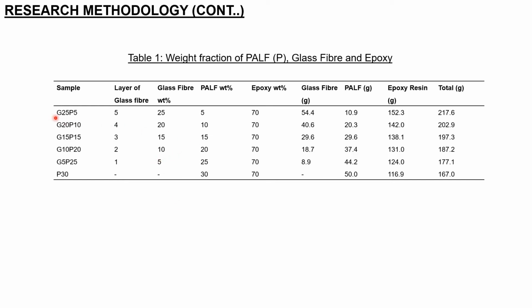Here is the table for the weight fraction of composition. The acronym G here is for glass fiber, 25 means 25% of glass fiber, P means pineapple leaf fiber, and 5 means 5% of PALF. The total percentage of glass fiber and PALF is 30, and the balance 70 is epoxy.